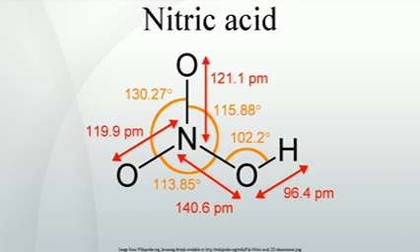Red fuming nitric acid, or RFNA, contains substantial quantities of dissolved nitrogen dioxide, NO2, leaving the solution with a reddish-brown color. Due to the dissolved nitrogen dioxide, the density of red fuming nitric acid is lower at 1.490 grams per milliliter. An inhibited fuming nitric acid, either IWFNA or IRFNA, can be made by the addition of 0.6 to 0.7% hydrogen fluoride, HF. This fluoride is added for corrosion resistance in metal tanks. The fluoride creates a metal fluoride layer that protects the metal.